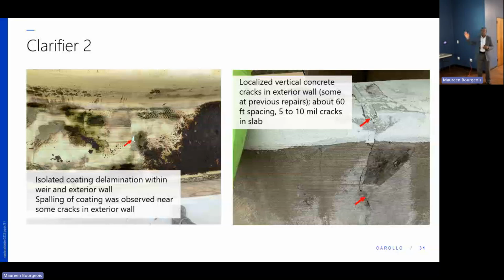At the openings also on the top slab there, we also saw some visible cracking right there. So those cracks also were evident at those reentrant corners in the openings at the top slab. But at the bottom though, it looked very good. There were no audible delaminations. So when we sound it, where it gives off that hollow sound behind it, we didn't see that at the bottom. And so the bottom of the wall at the wet well is in good condition.